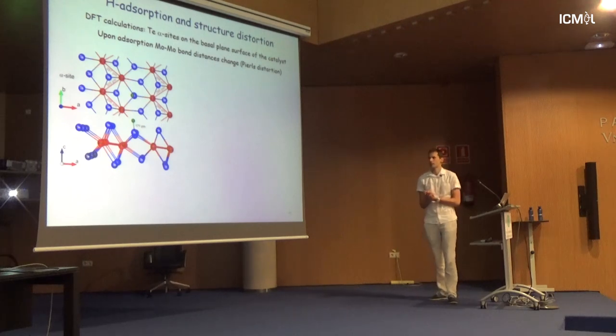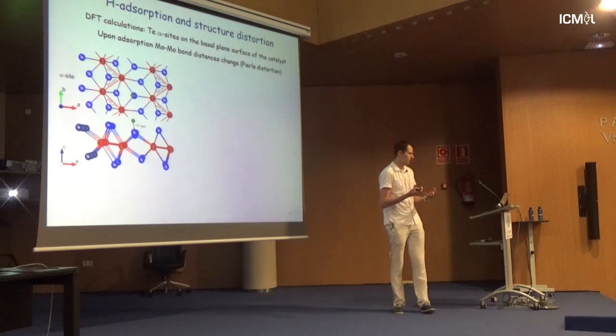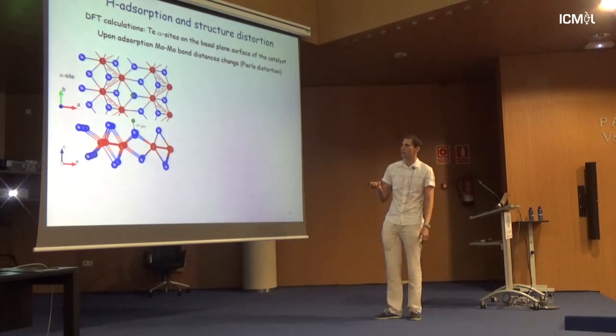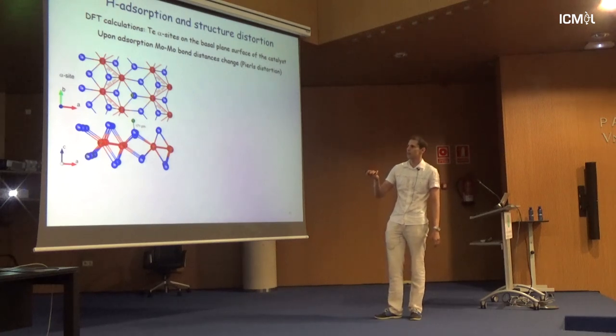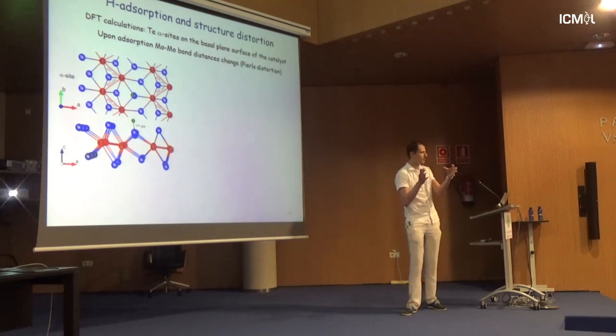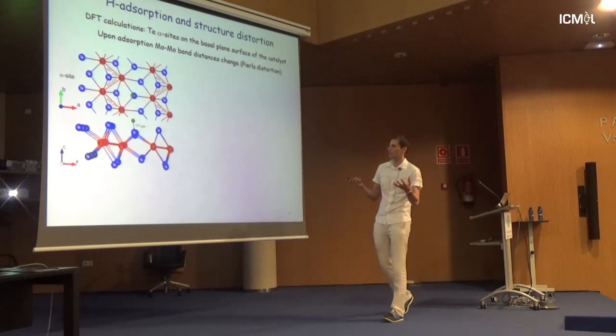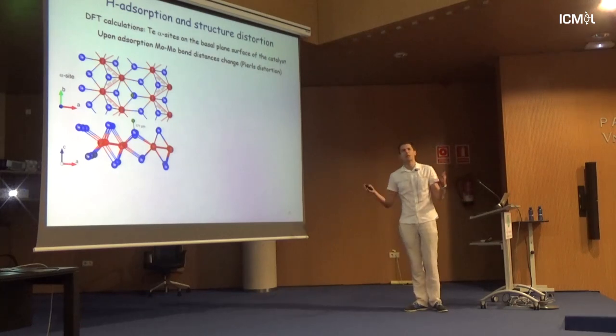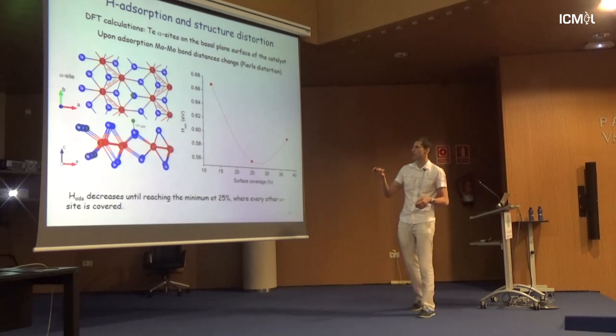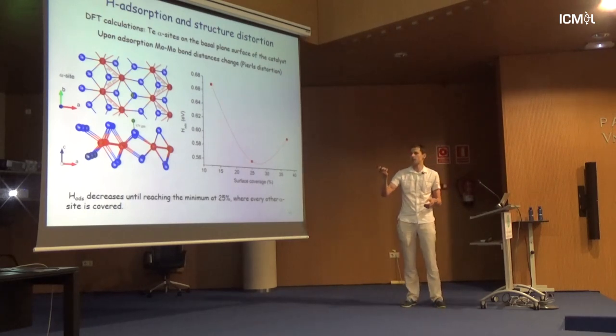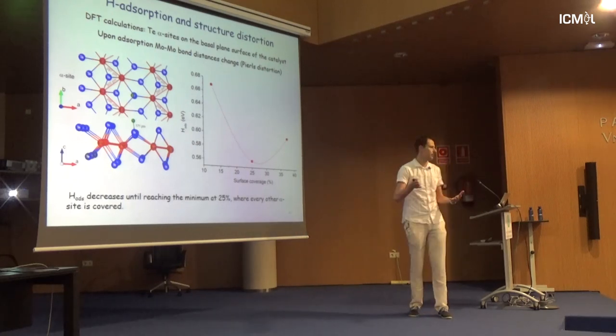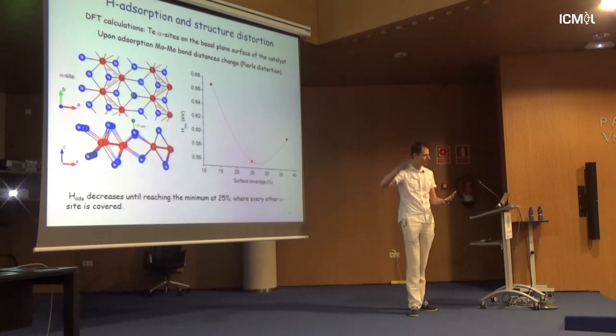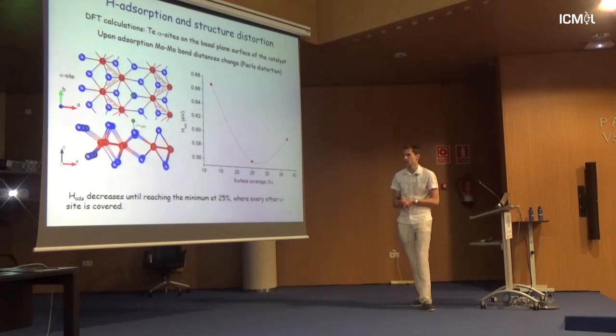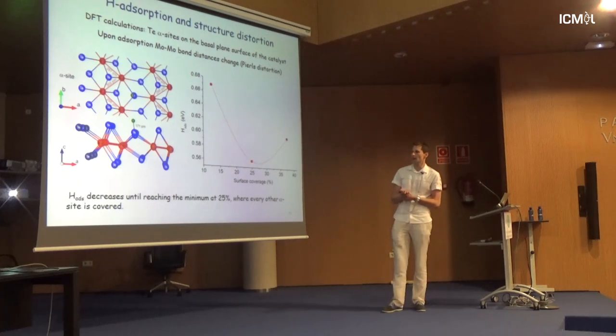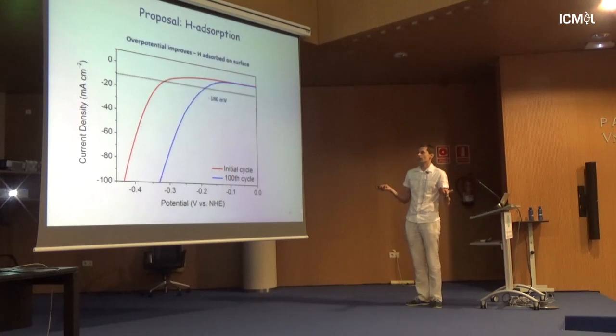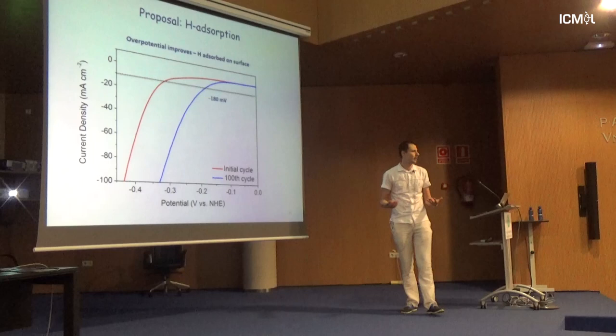So we also did the DFT calculations to see what the effect of hydrogen adsorption is. So when hydrogen adsorbs on the surface, we have a shortening of the bonds, at least in theory. Again, this is what our calculation is showing. So the bonds are getting shorter, and this may cause some dynamic structure change. And you can also calculate and you will find there's an optimal surface coverage. So that's the reason it stops. So it does not go activated into infinity. You keep cycling, but it stays at the same overpotential. So it reaches a specific minimum. Okay? So, as I mentioned, the proposal is, as hydrogen adsorbs, we have a change in electronic structure.